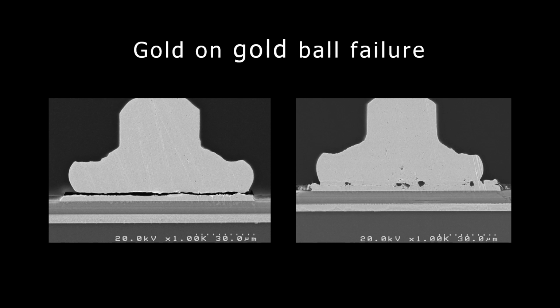Compound semiconductor devices typically use gold bond pads and gold bond wires. With gold on gold, no intermetallic region forms. If the gold bond pad is contaminated, failures will occur.